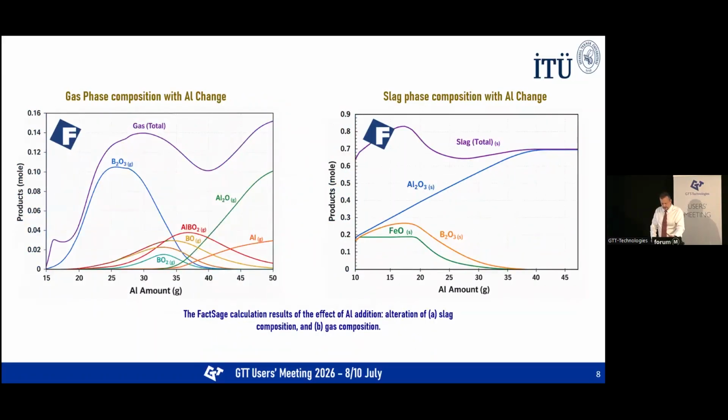Unfortunately, the SHS process is not perfect because gas formation occurs, especially when we use boron, silicon, and manganese oxides. Once the gas leaves the crucible, it is not part of the system anymore, and it is quite difficult to estimate the whole process.